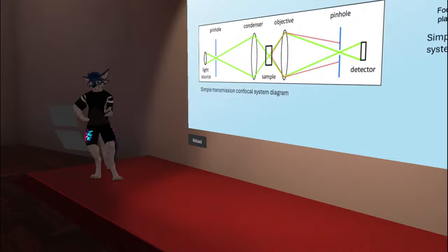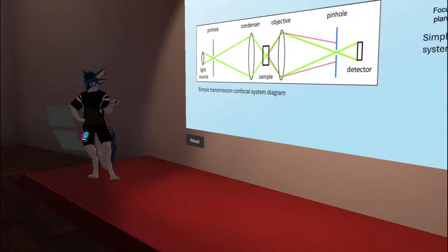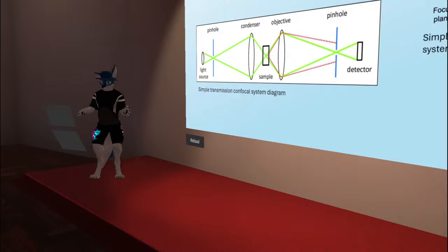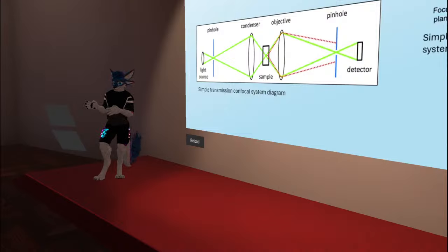Though there is some non-destructive testing, again with things like polarization microscopy, because it can see things like stresses. Imagine you have a big wafer and you put a couple hundred layers on there, and maybe you want to image how that's stressed. Polarization microscopy offers a potential avenue into that kind of non-destructive testing.